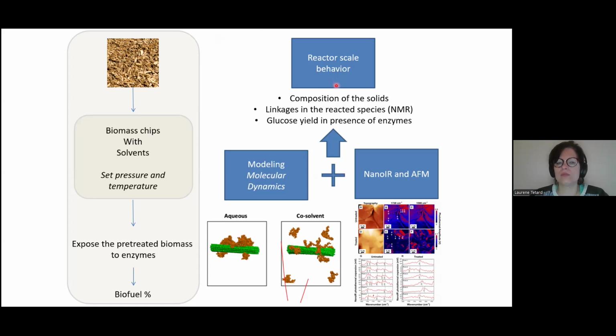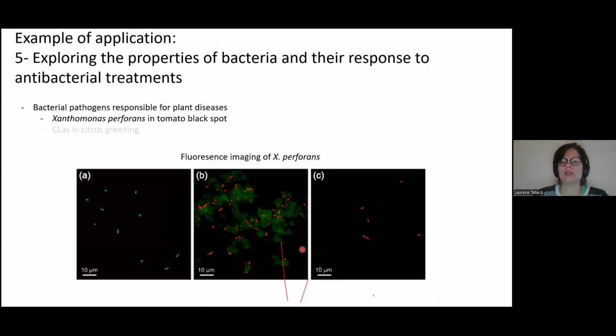So that was one of the first studies where we started to try to figure out how our small scale measurement could impact the understanding of larger scale measurements that are more standard for the field. And in this case, it was very successful because we were able to pinpoint which mechanism the molecular dynamics were predicting that were the most likely based on the infrared spectra we collected.